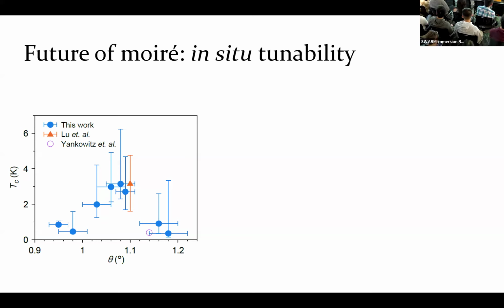And you make that device. And if you want to change the twist angle, you have to make another device. And actually, that's what we've been doing so far in this field of studying these Moiré materials. For example, if I want to study superconductivity, what's the temperature for the superconductivity as a function of the twist angle, then what I need to do is basically make tons of devices, tens of devices, or even 100 devices. And then I try to get some trend out of these many data.